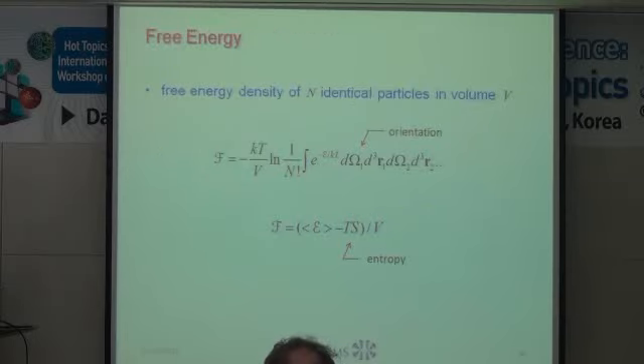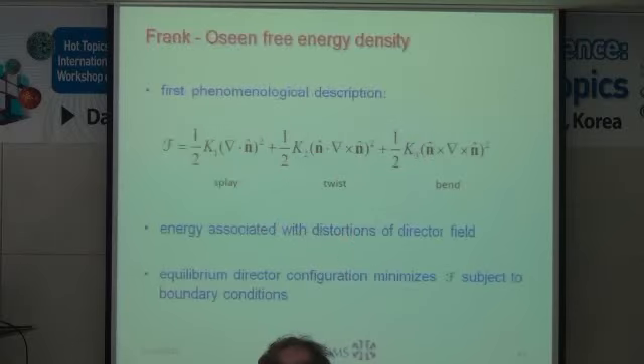So the free energy, a fairly robust definition of the Helmholtz free energy density, is this quantity here. So one basically needs to enumerate all the possible states, and this is the density of states with energy E, and then one has to sum this over all orientations omega and positions R. So one has to try to evaluate this quantity somehow for the system, take the logarithm, and that's it. And this turns out to be equivalent to the average energy minus TS, where S here is the entropy. So to some extent, the business is to write down a free energy and to minimize it.